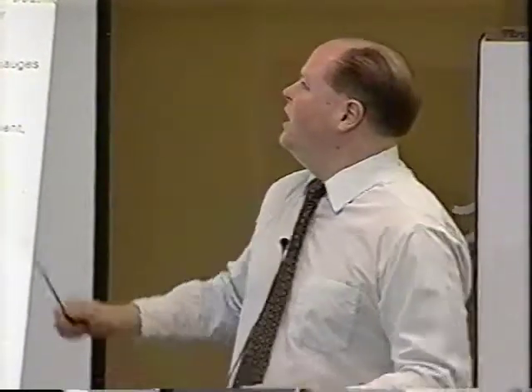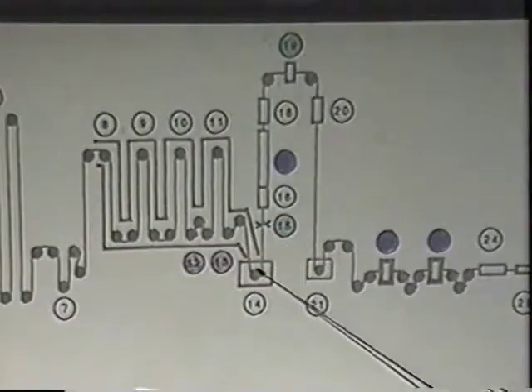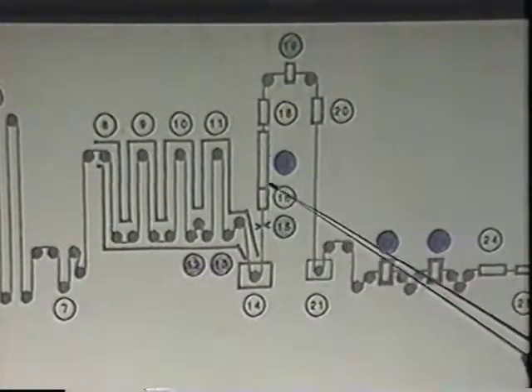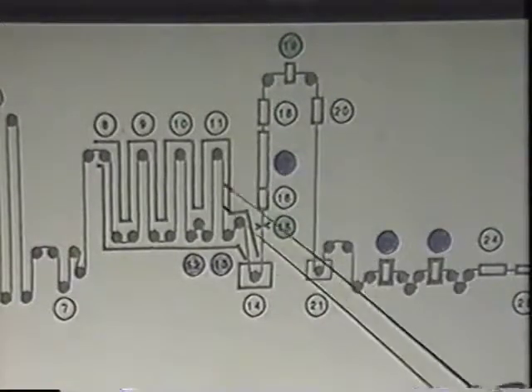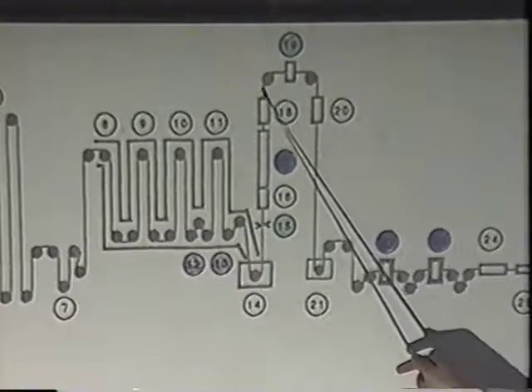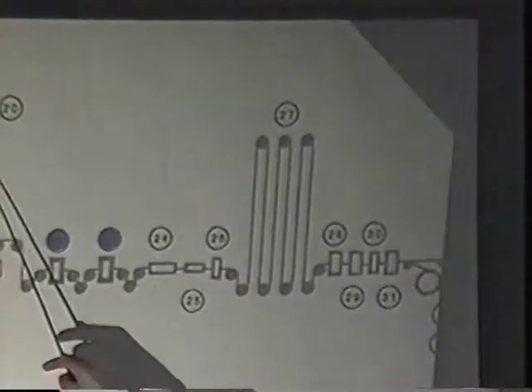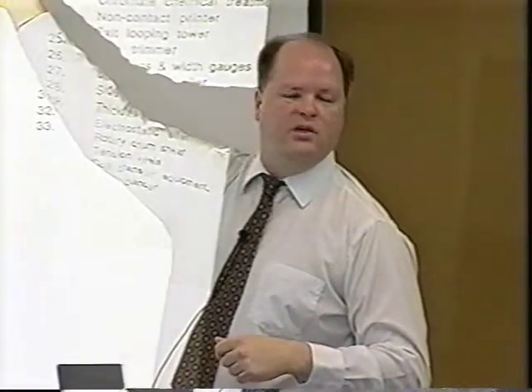Yes? What sort of heat is maintained in that area? Like I said, the strip was about 860 degrees. The pot's about 860. The strip, there's some cooling zones here because we want to cool the strip down because this is still molten zinc on there. So we want the zinc to solidify before it hits that turnaround roll. That's part of the reason why that building is so high: you don't want molten zinc on the strip when it hits a turnaround roll. Otherwise that roll is going to get all gunked up and be a mess.